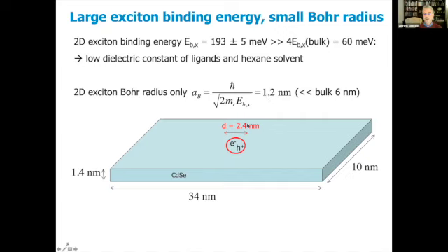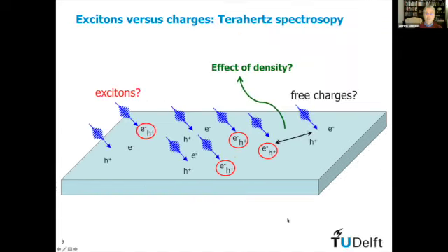So the diameter of the exciton is only 2.4 nanometer, which is much smaller than the about 6 nanometer exciton Bohr radius in 3 dimensions. So we get small, tiny excitons that are flat, confined in the vertical direction. Now, coming back to the research question, that was, if we excite such a nanoplatelet with many photons, what is then the effect of density? Do we get excitons all the time, or do we get free charges?